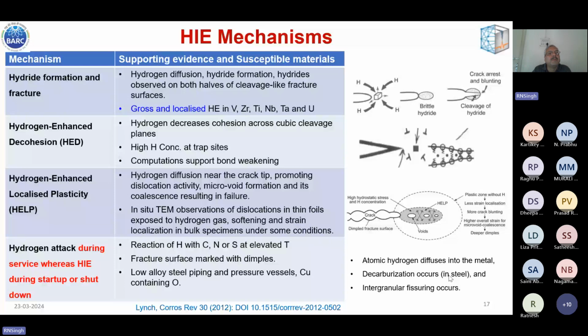If you look at the mechanism, hydride formation and fracture: here hydrogen diffusion takes place under the chemical potential gradient. And once the local solid solubility is exceeded, hydride formation takes place. Some experimental evidence is there that if you see a fractured surface, then hydride is observed on both the halves. So it means that it is the hydride which cleaves apart, not the debonding of the hydride and the metallic matrix. So both gross and localized hydride embrittlement is exhibited by metals like vanadium, zirconium, titanium, niobium, tantalum, and uranium.